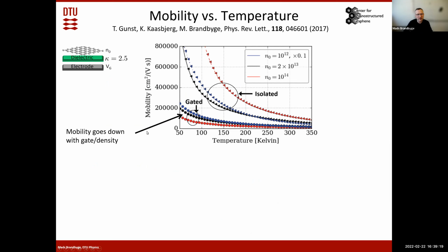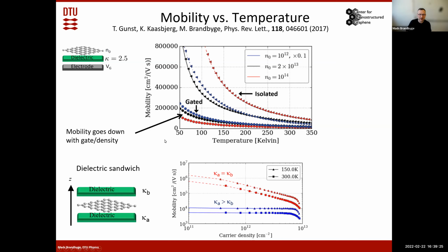this may not be the sole effect, but the upshot of this is that the symmetry in the device should matter. So if you could make it perfectly symmetric, so you have a perfectly symmetric gating electrode with symmetric dielectrics around, then that should impact the mobility. Then you could get a much better mobility because you would reduce the coupling to the out-of-plane vibrations. So far, this is just a theoretical proposal, and I've not seen any experiments which really document this. Probably also because it is somewhat difficult to control the symmetry in the device.